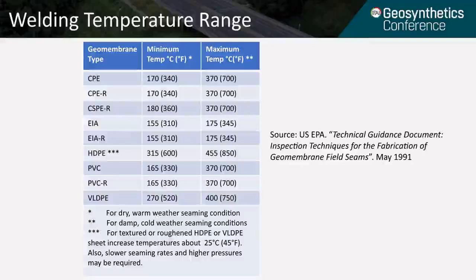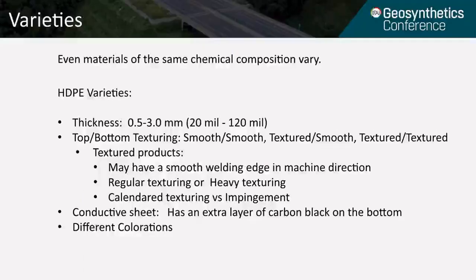It also shows that reinforced materials as designated with a -R, such as PVC-R below it, are welded typically at the same temperatures as the non-reinforced materials. Even materials of the same chemical composition vary widely. If you look at HDPE, there's a bunch of varieties. The thickness can range anywhere from 20 to 120 mils.